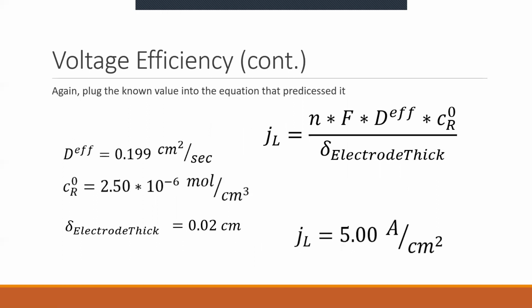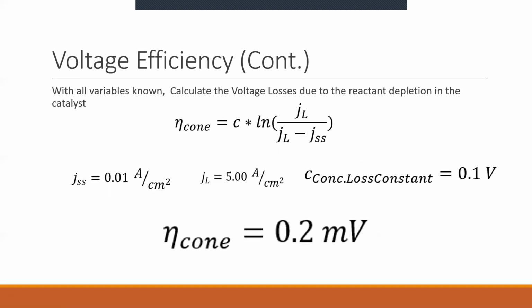With our effective diffusivity known, we can calculate our limiting current density. The limiting current density, JL, is the condition that will occur when reactant concentrations in the catalyst drop to 0. This represents the highest current density the fuel cell could physically reach. All factors have been used before except the bulk flow reactant concentration, CR, and the electrode thickness. With these parameters plugged in, we yield a limiting current density of 5 amps per centimeter squared.